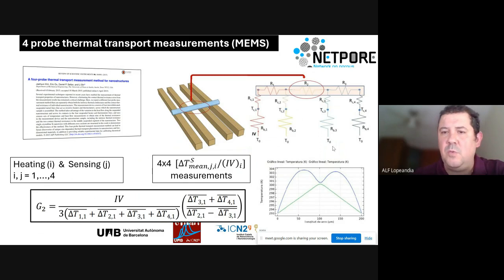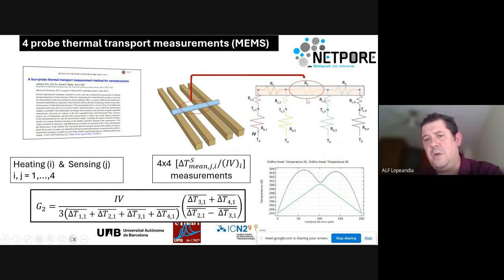In fact, this is the heat transfer equivalent circuit. Here we have different resistances: the resistance of the beam from the central point to the silicon frame, and we have the thermal contact resistance also. And then we have the thermal resistance of the piece of nanowire between beam 1 and beam 2, R1, the thermal resistance of the piece of nanowire between beam 2 and beam 3, that is R2, and the piece of nanowire that will be represented by R3.